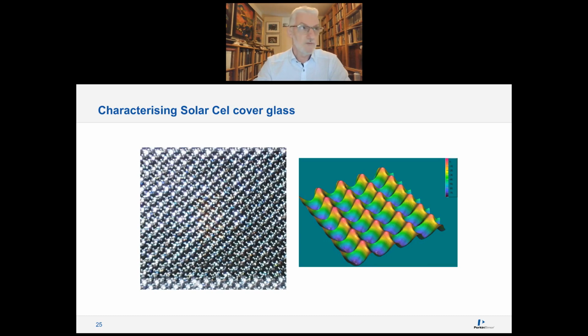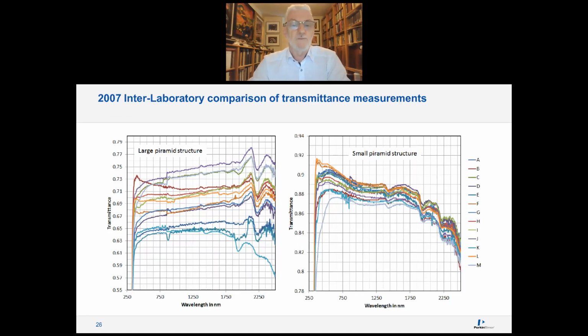They found out around the beginning of the century that it was virtually impossible to get decent transmittance measurements and reflectance measurements from this. In 2007, we had an interlaboratory comparison with several laboratories, I think 16 or 18 laboratories. These laboratories are normally capable, if you have a float glass sample, just a flat, smooth glass sample, of measuring the transmittance within 0.2%. That's the agreement we typically get with this group of laboratories.